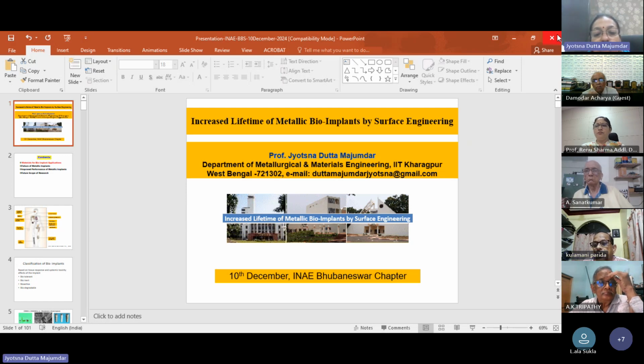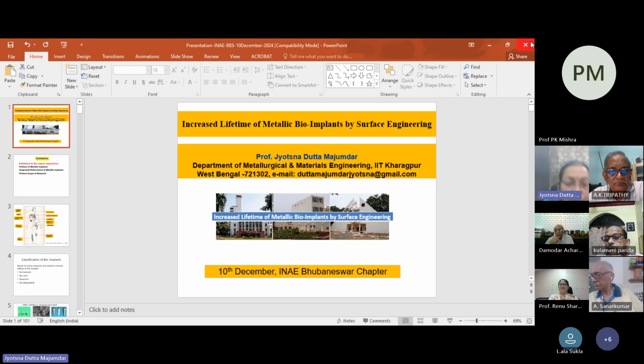Oh, you are talking about polymeric coating on this titanium surface. Yes, sir. Polymers are usually quite soft, so it cannot be applied for wear resistance applications. But we are also going to apply a very thin polymeric coating for antibacterial property enhancement. So that is very thin, 1 or 2 atomic layer deposition on the surface, so that there is no biofouling corrosion. But this is not applied for wear resistance applications.